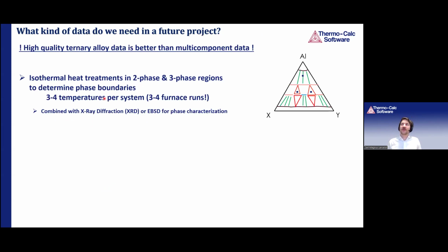And what experiments do we need to do? I want to emphasize that it's most important to generate high quality ternary alloy data, much better than multi-component alloy data. Multi-component alloy data is good for validation of the database and identifying areas of improvement, of course, but high quality ternary alloy data is important to be able to improve the database. So a very cheap method is to make isothermal heat treatments. You define, here's a schematic term.